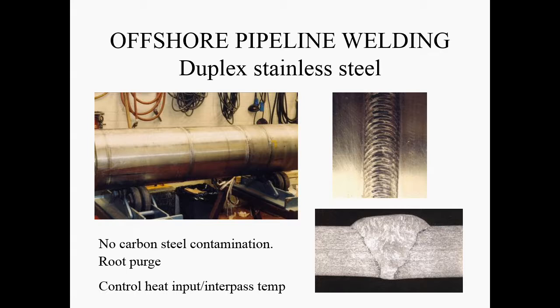Why it's important to keep the interpass temperature within these limits. So, in terms of the mechanical properties of the pipeline materials, we said that for the API grades during welding, one thing that you need to avoid is high cooling rates, because high cooling rates suppress diffusion, and we end up with those phases that are hard and brittle in the heat affected zone.